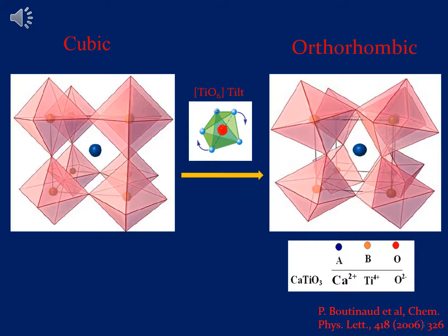Now, this happens because the structure accommodates the inner ion by collapsing the inner octahedral site by simply tilting the corner-sharing oxygen cages. Now, there is an orbital overlapping that exists between the A and the B ion. Now, the collapse of the inner octahedral site will reduce the distance between the A and the B ion, and consequently, the stronger the overlap will be.